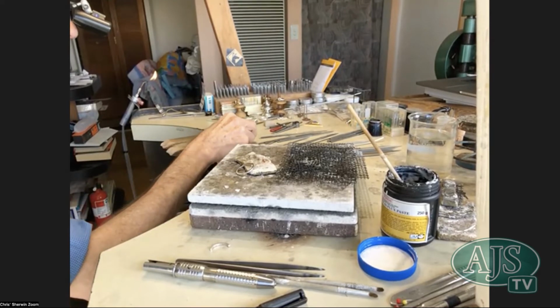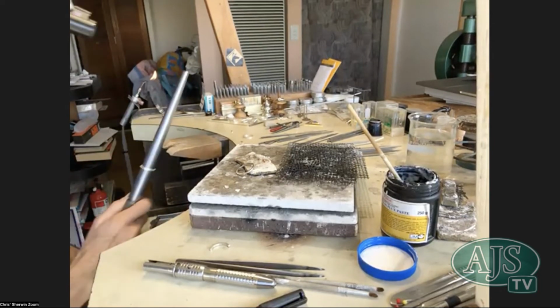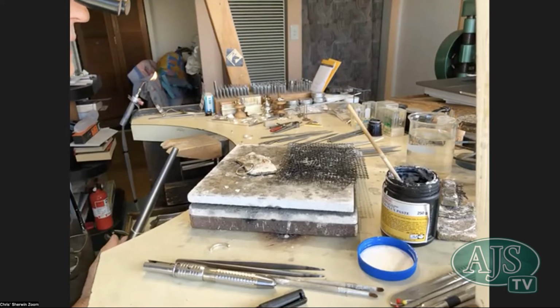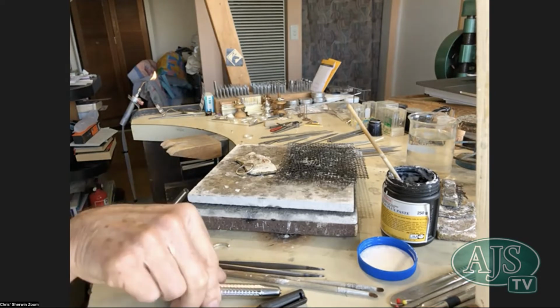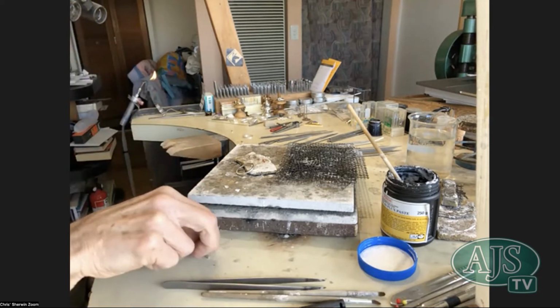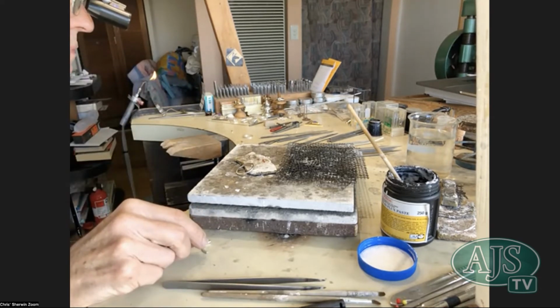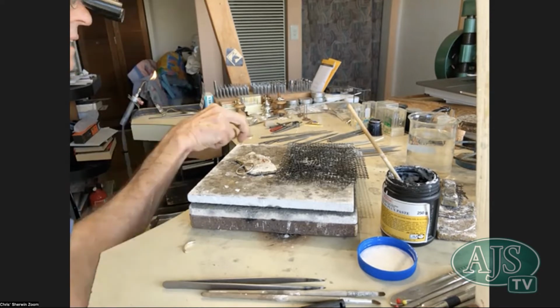Good practice is like a jeweler would always just find the join and then redo the join through the join. That's right. That little trick of heating up the band gently just to the point of oxidation of the copper will identify your joins. So in gold, you'll get little shades of purple and dark brown, and you'll see where all the little shiny bits of solder are going vertically down through the band. And it's just important to identify where they are because you're trying to make a living and you don't want to be fixing up what other people do.